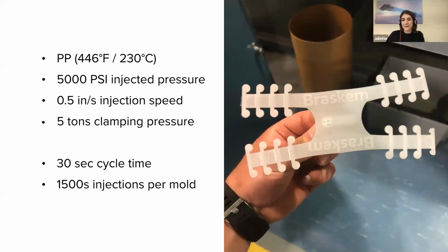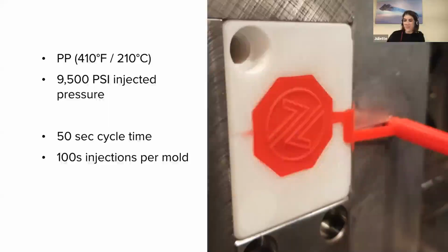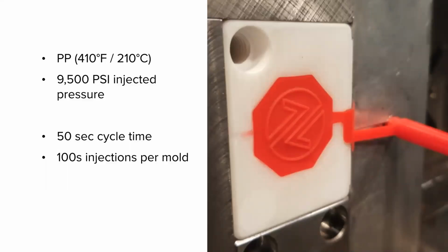Great. So that's a good transition to the next, to Mark's mold, that is a more complicated geometry. So Mark, maybe you can share what were your conditions? Absolutely. So Jake, I was asking because ours correlates to that as well. Our polypropylene, I believe, was like a 30 melt that we were running. We try and run on the low end of temperature. So I believe Jake made his mold out of the high temp resin. We're running in the 10K rigid. So we're trying to keep down in the lower injection ranges on this. Our pressure, we were running about 9,500 PSI on this.